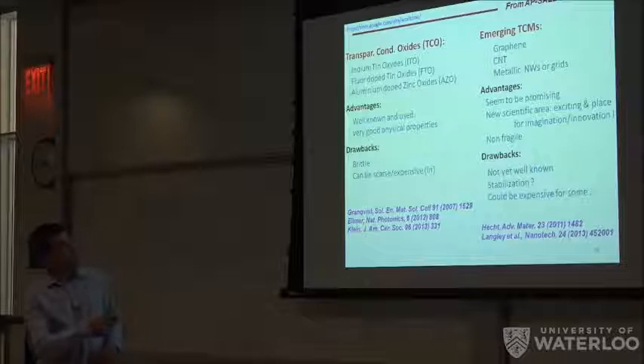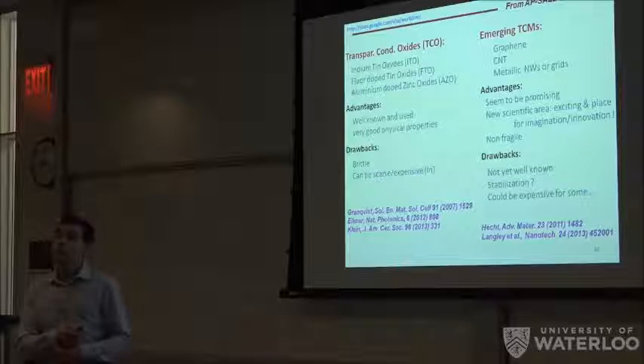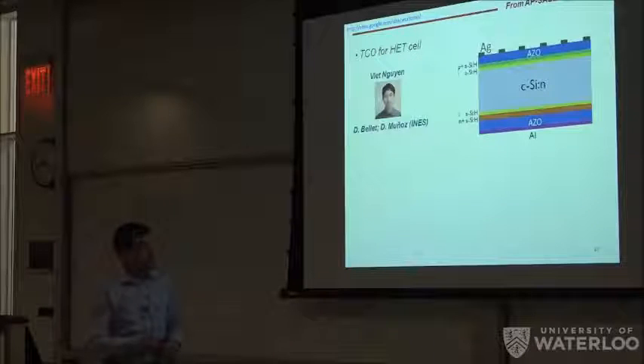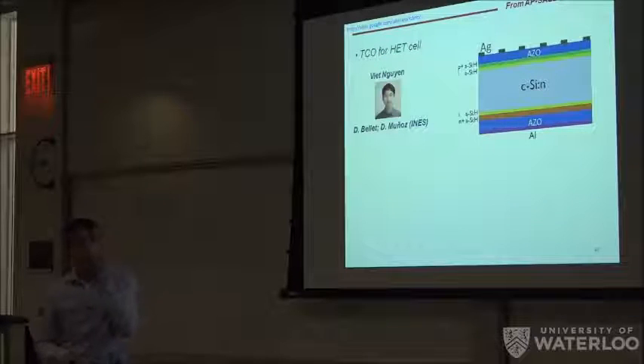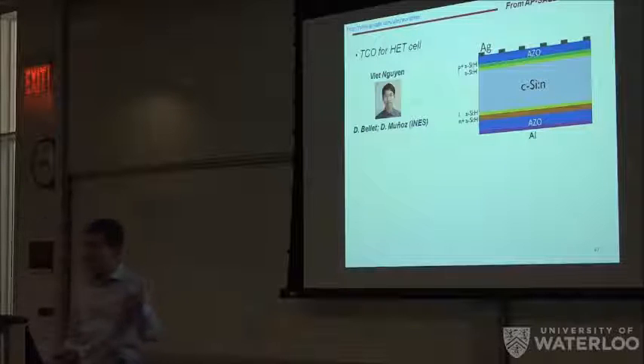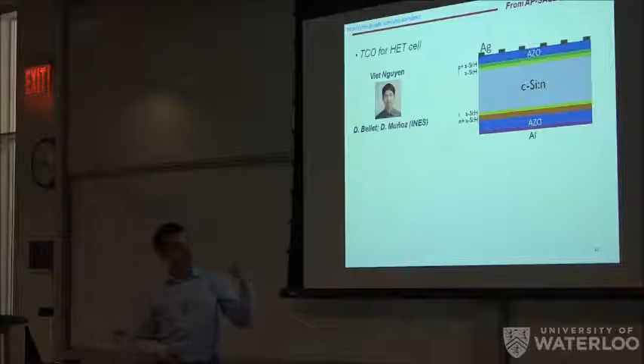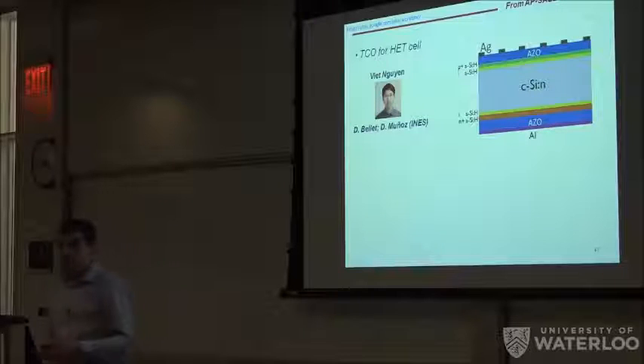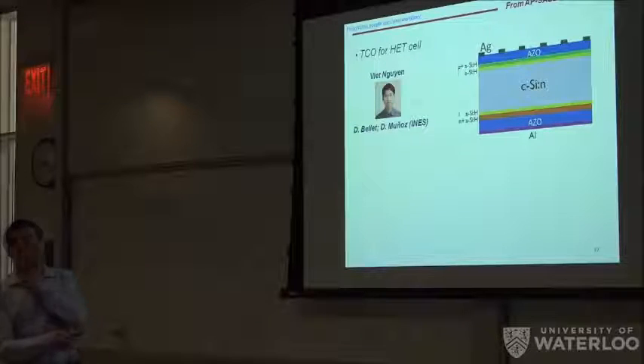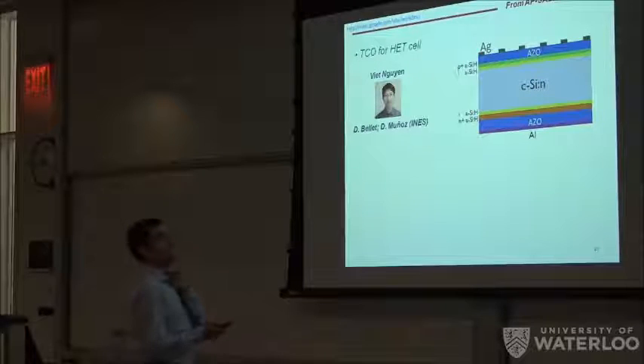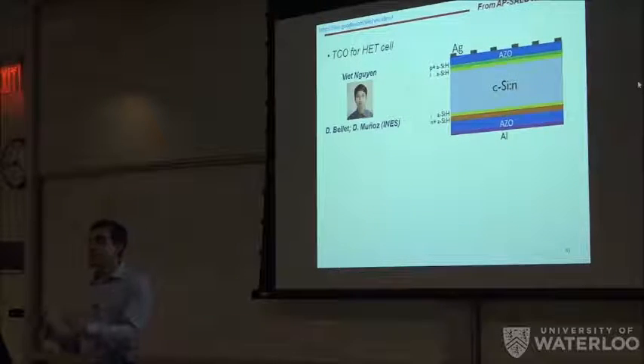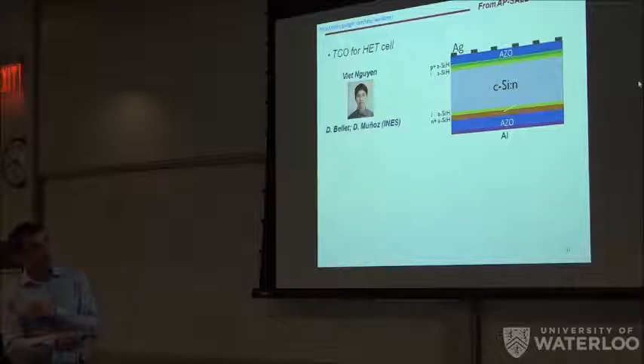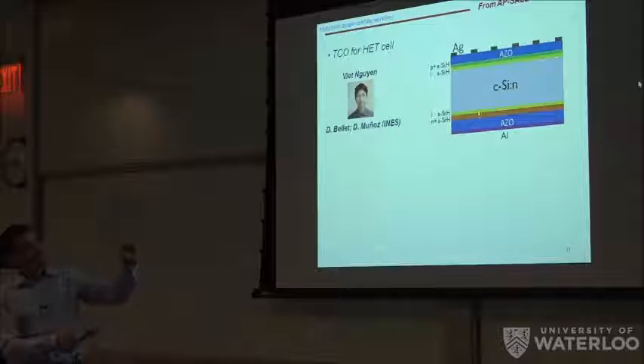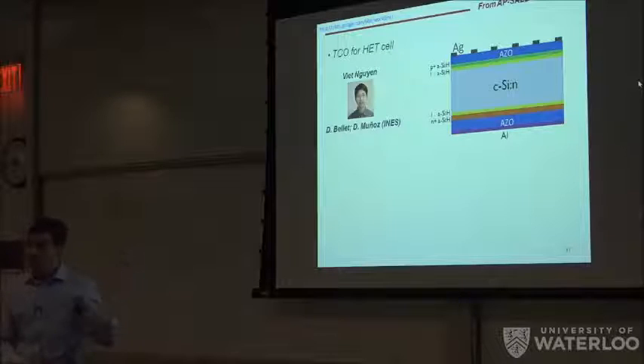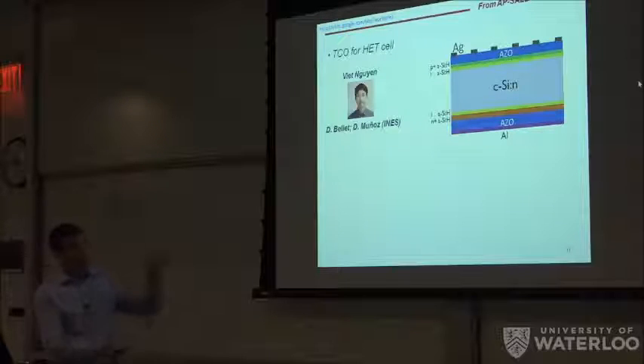So as I say, we're focusing in the lab on FTO, aluminum doped zinc oxide, and transparent conductive materials based on silver nanowires. And in the first example, again, we're trying to take advantage of the properties of spatial atomic layer deposition to enhance the performance of a device. In this case, the system is heterojunction solar cells. And this type of cell is very similar to a crystalline silicon solar cell. But what we do is we have the crystalline core, and we passivate it with a thin layer of amorphous silicon, which is doped P and N on each side.